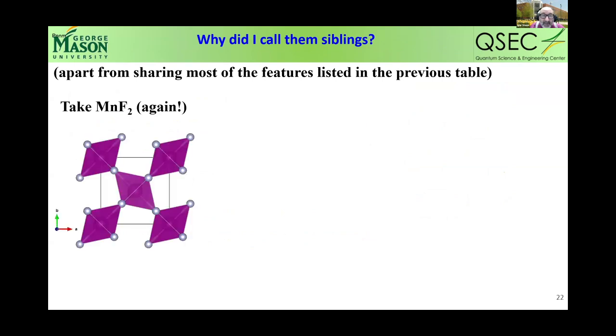And final slide. So why did I call them siblings? Not only because they have similar properties, and as I say, sharing most of the features. Let me give you an interesting example. Take manganese difluoride. Before, I was showing a single layer, and this material doesn't exist in single layer, so it was just a sort of a theoretical exercise. But you can apply strain to this material. If it's unstrained, then you have manganese, which has double degenerate Wyckoff position. When it becomes magnetic, it becomes altermagnetic.